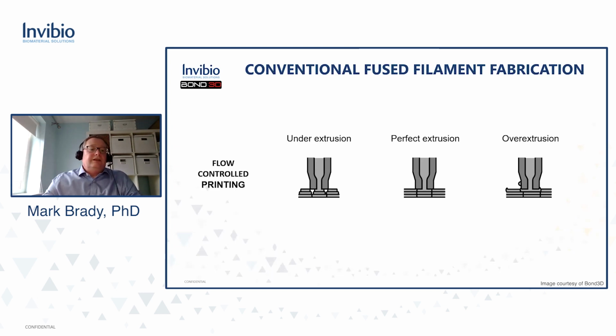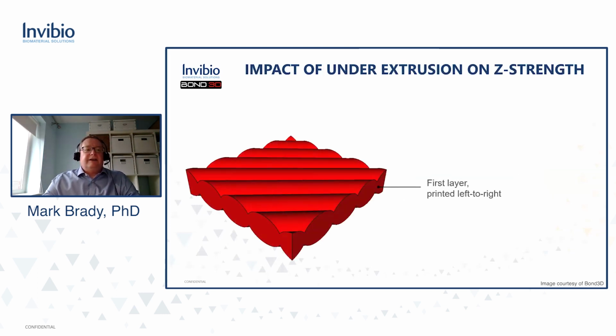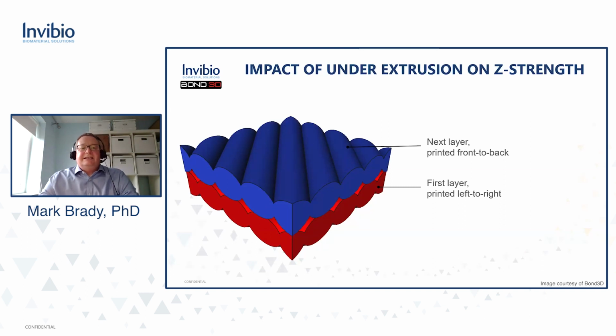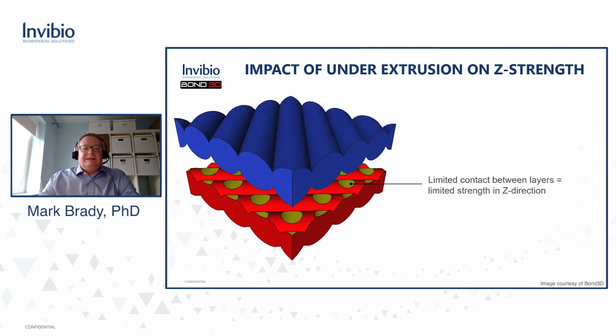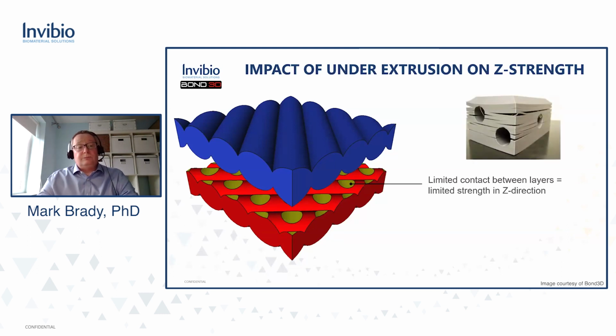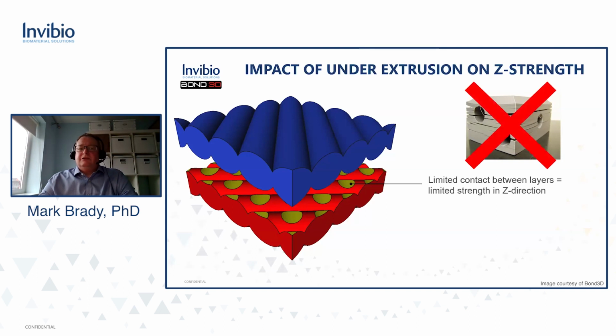So let's take a look at the impact of that under extrusion on the critical part strength in the Z direction. If you take a first layer, for example, you can see the slightly elliptical shape of the deposited filament when you look end on. And then the second layer is often laid down at 90 degrees to the first layer. With traditional flow control printing, where the material is meted out consistently and calibrated towards slight under extrusion, you can get these areas of limited contact between the layers. That can leave voids and can have an impact on the subsequent Z strength, the most challenging area where you need to achieve high strength, and that can result in delamination.